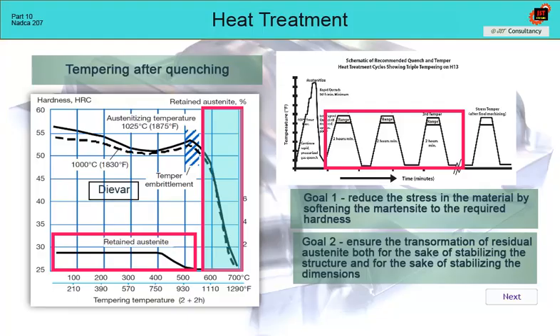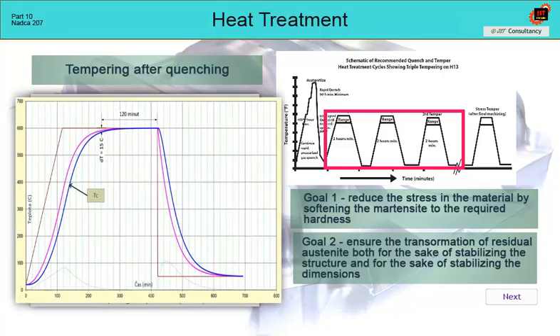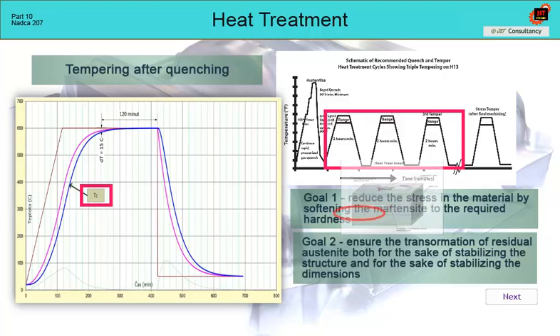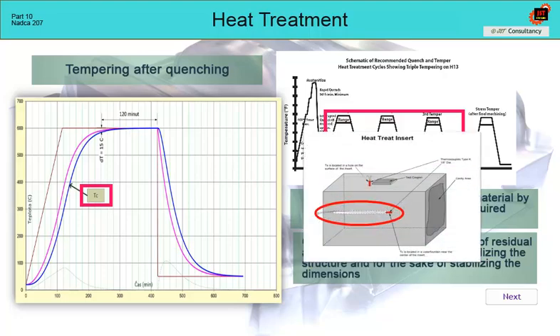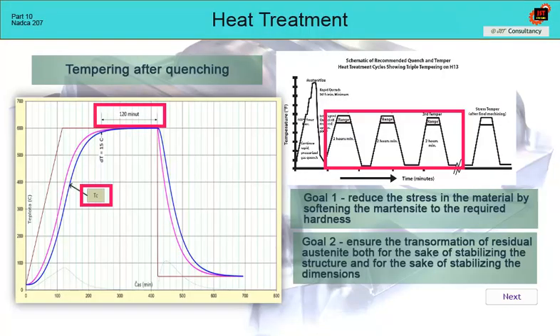The recommended tempering temperatures are also adapted to this. For a properly conducted tempering cycle, it is necessary to be able to establish the core thermocouple Tc and thus measure the temperature of the piece. The tempering time is at least 2 hours and is calculated from the moment when Tc reaches a required temperature with the difference of, for example, 15 Celsius. The delta T parameter is up to the heat treater, but if he determines it, he must use it in the long-term time period to ensure the reproducibility of the results.